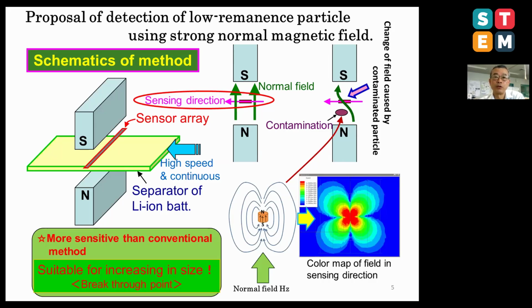These are the schematics of a measurement system. A strong magnetic field in the normal direction is generated by strong magnets, and the thin film sensors are set in the magnetic field as a sensor array. In this system, a high sensitivity thin film sensor is used, and its sensing direction is arranged along the horizontal direction. The reason the sensor is placed in the horizontal direction is that the thin film sensor has a tolerance against a strong magnetic field along the surface normal direction of the sensor film. It's due to the demagnetizing force.